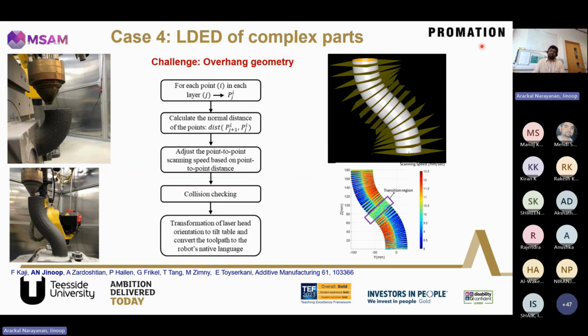So we could see that when you slice this particular geometry, one region has got a lower layer thickness, another side has got a higher layer thickness. So just by controlling the scanning speed within a single layer, we can control the material deposition or the quantity of material deposited, and then we can use it for making these sort of bent pipe structures. So we use lower scanning speed at one region, and a higher scanning speed in another region.